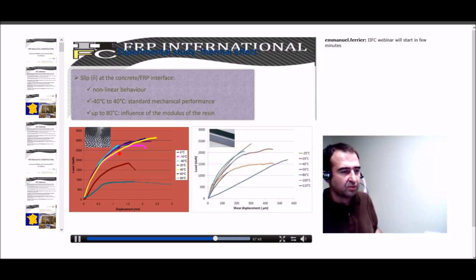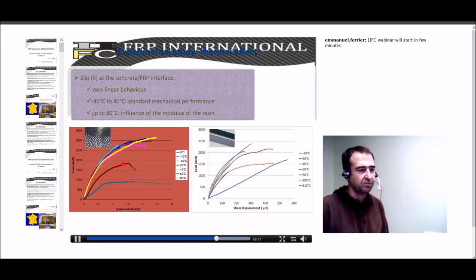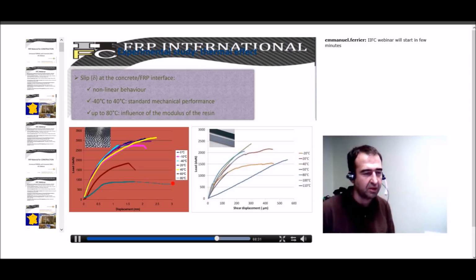In this case, you can observe that from -40 to +40 Celsius, including 0, -10 and 20, there is nearly no change in mechanical properties. There is a slight increase of the stiffness for very low temperature and a slight decrease in strength, but there are not so many changes. But when you reach 60 Celsius, remember that the glass transition temperature is about 75 for this polymer, the decrease starts, and then at 80 Celsius you have a very important decrease with non-linear behavior, mainly depending on the FRP. Same observation with laminates. The temperature was higher. You can observe here that we start to get some important decrease only at 100 and 110 Celsius.